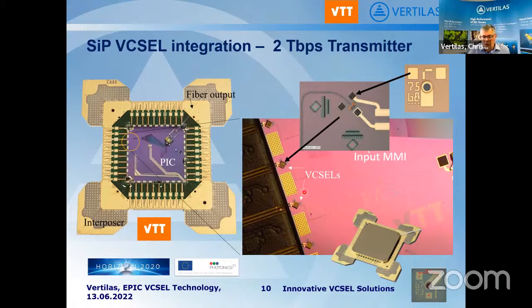So you can see here a sketch. This is 1 VCSEL on each side. You have 10 VCSELs flip chip bonded. Here you have a zoom in. You can see the 3 contact pads for this VCSEL chip, and then those lasers are flip chip bonded face down and are coupled into the waveguides with a 45-degree mirror. And by that, you can integrate 40 VCSEL chips in a very small form factor, and they were driven by DMT up to 50 gigabits. So you had a 2 terabit transmitter and a very small form factor. And of course, here the VCSEL part is very important, the performance and the low power consumption.